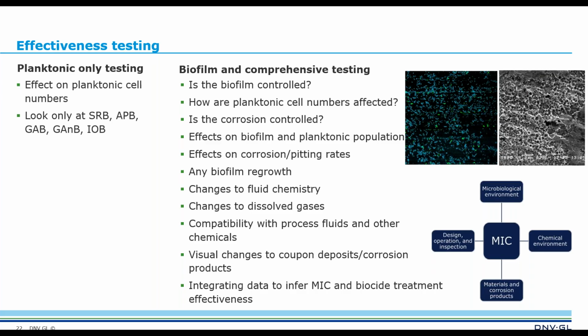Most often, this is a step that's missed in all of this biocide testing that is done in the lab, where the focus is maybe only on the planktonic population or the biofilm population, but not on corrosion. But if we are applying biocides to mitigate MIC, we should not forget that corrosion rates and pitting rates are important to also look at.